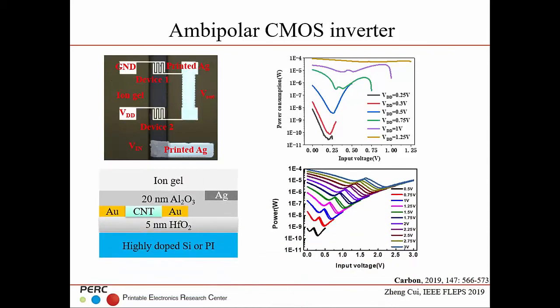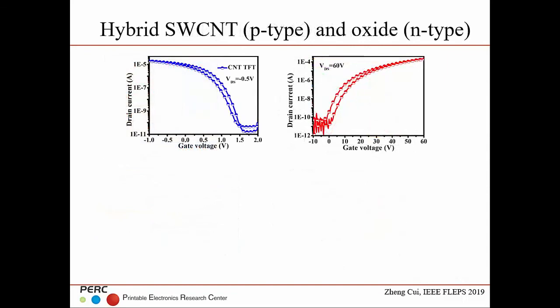And also for this one, it's not quite environmentally stable, so we cover it with aluminum oxide, and it gave this ambipolar CMOS inverter, which has a very low power consumption. So let's come to the hybrid. We know that metal oxides are always N-type, and carbon nanotubes P-type. But unfortunately, normally the metal oxide has a very high controlling voltage compared to the carbon nanotube, only a few volts or less than 1 volt, and this is tens of volts. So we first need to change this metal oxide to match the carbon nanotube, so they can become a pair to be in the CMOS inverter.